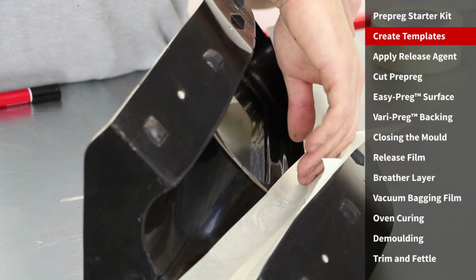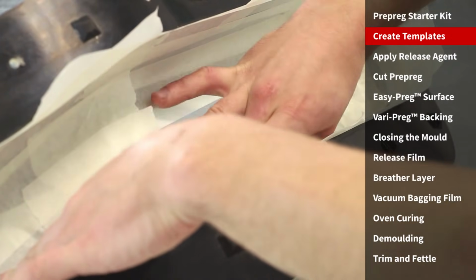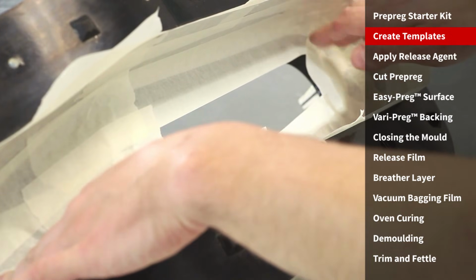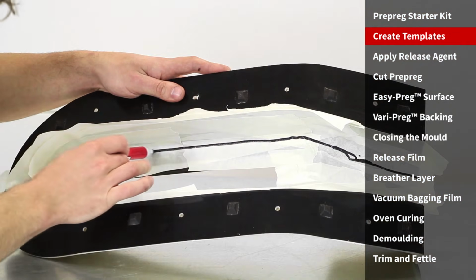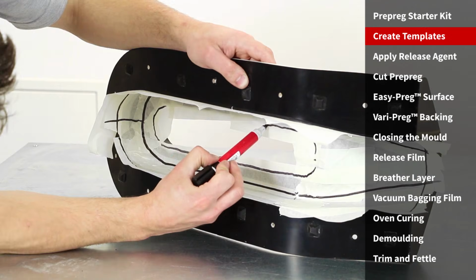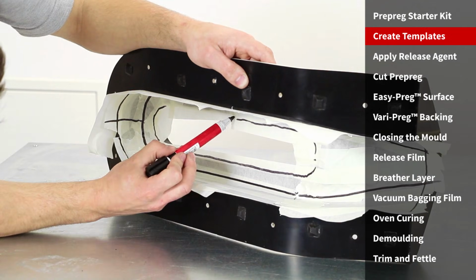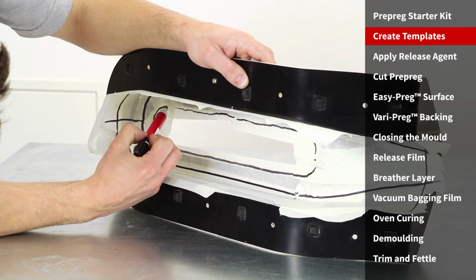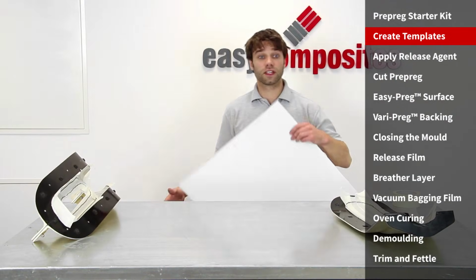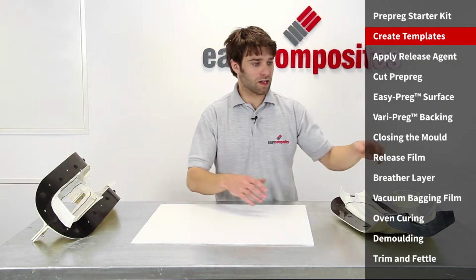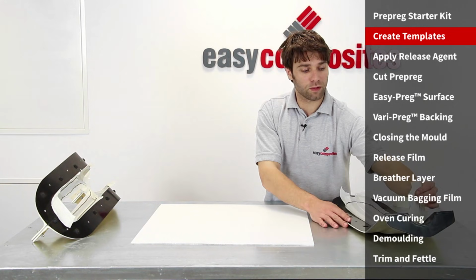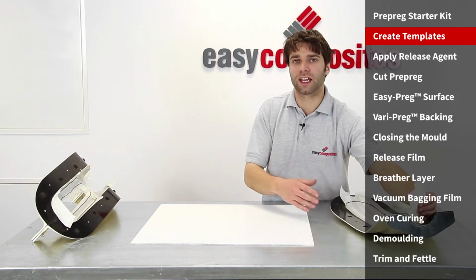When deciding where to put cuts in the material, you should consider both the cosmetic appearance of where the join will be and also the ease with which the part can be laminated. In many cases, this will mean locating the join in a corner on the mould. Corners visually hide the join and also make it easier to lay up without bridging. You can transfer these templates that you've made onto any material that you like. We're going to be using fluted signboard as it's very easy to cut and fairly durable.